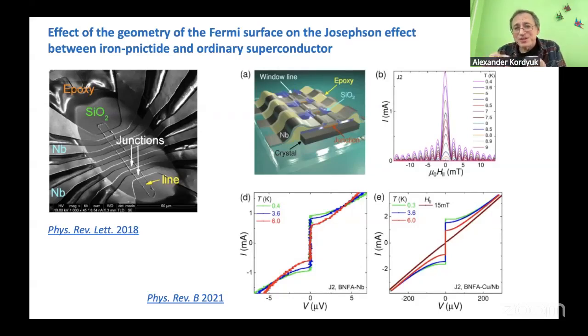It is because of destructive interference, when you have transitions from plus to minus and from plus to plus, and therefore you have a phase shift, and they are almost similar, and they almost kill each other. And this is actually the case for all high-temperature superconductors, also for cuprates. So you remember I told you it is d-wave symmetry. It is also sign-changing symmetry, and it is also so for iron-based superconductors.